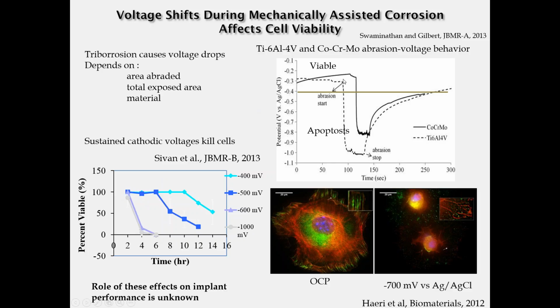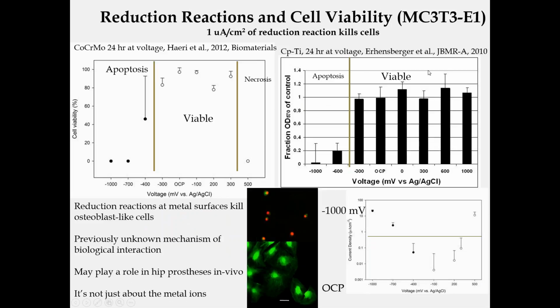This curve in the upper right shows that when you have abrasion of a metal surface in physiological environments, you can easily have the voltage drop within this range where the viability of cells on that surface can fall away, and you can induce cellular apoptosis, mostly because of the release of these reactive oxygen intermediates I mentioned earlier. We've seen this now both on commercially pure titanium, where below minus 300 millivolts, we go from viable to pretty much all dead cells cultured on these metals. Similarly, with cobalt chromium, there is an electrochemical zone of viability that ranges from about minus 350 millivolts to about plus 300 millivolts.